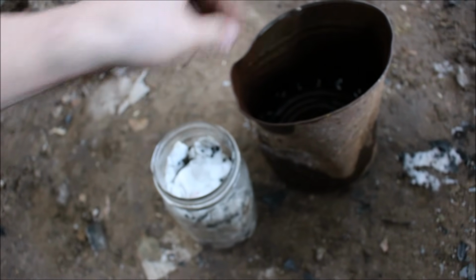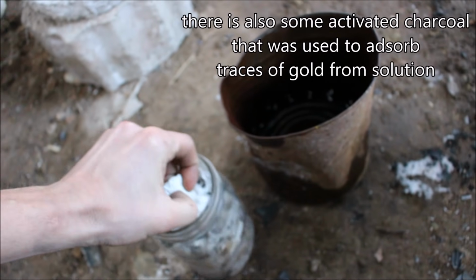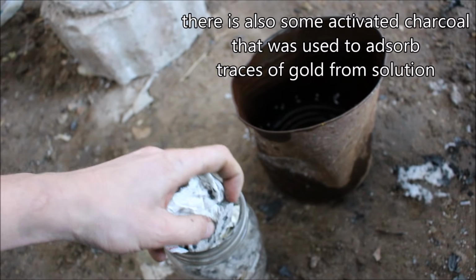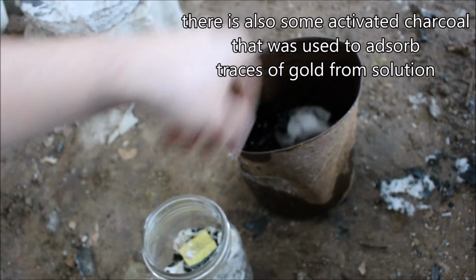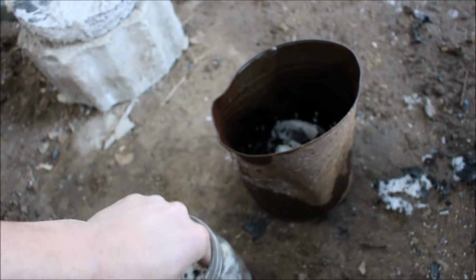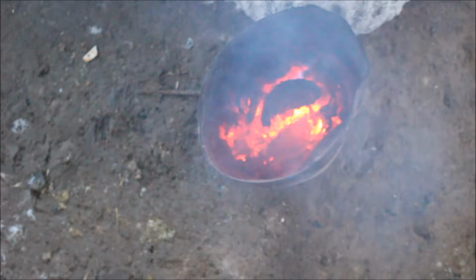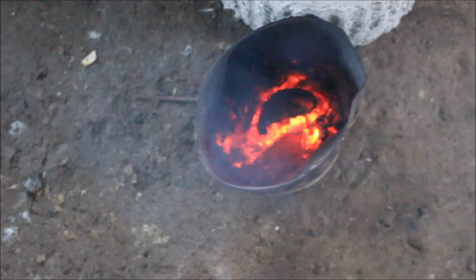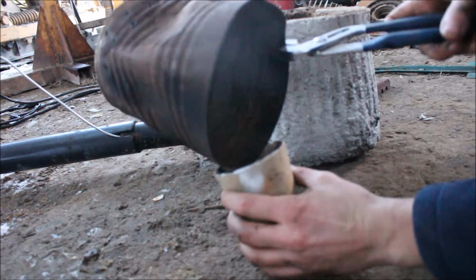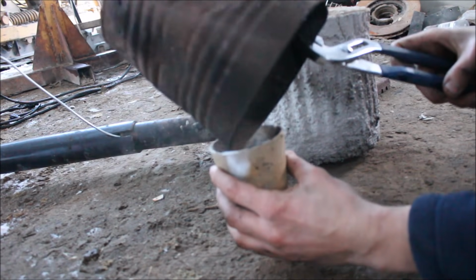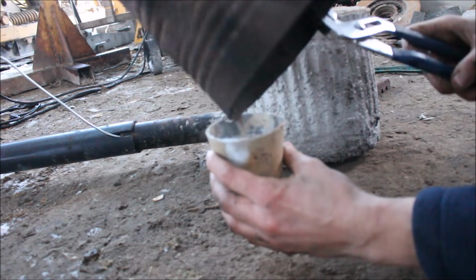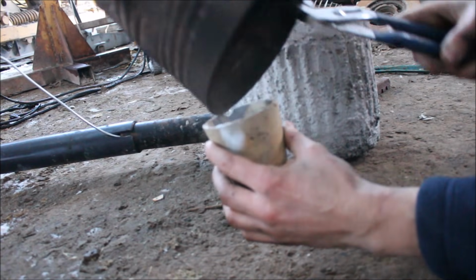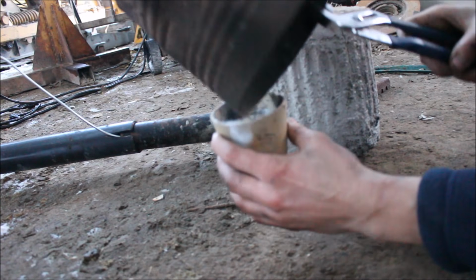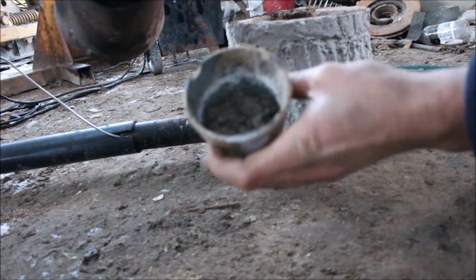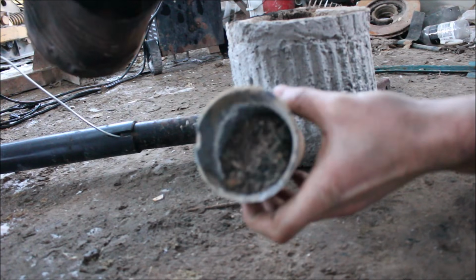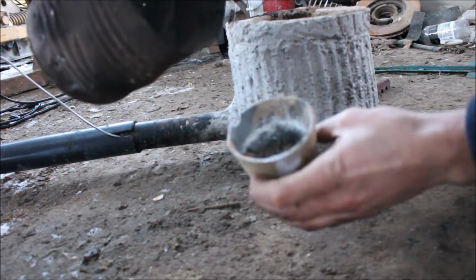So the first thing to do is to get all these rags and turn them into ash. Burn them up so that they take up much less volume. Got a sponge in here too, apparently. Now that this has been converted mostly to ash, I'm going to go ahead and transfer it over to this crucible. Might have to find something to wipe this out real good, but there you go. See that? There's my gold powder mixed with ash. And now I just got to get it out.